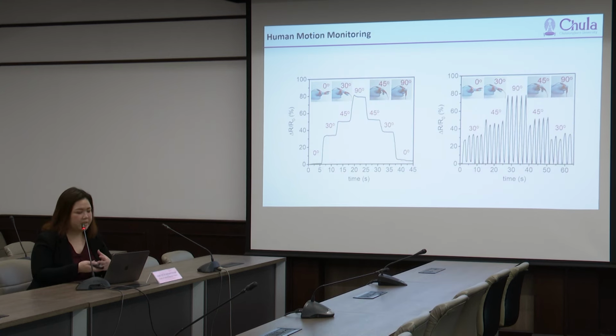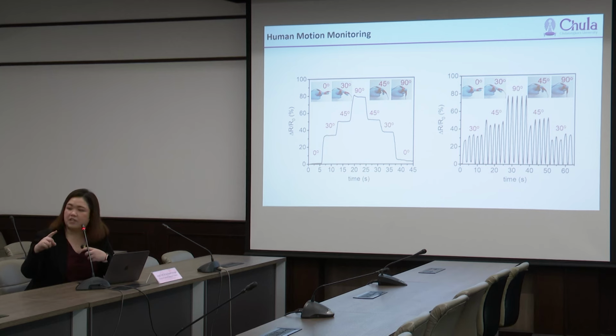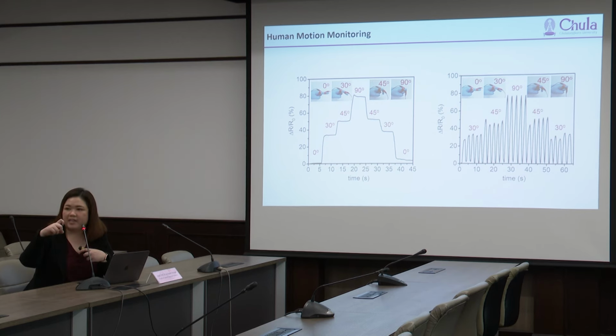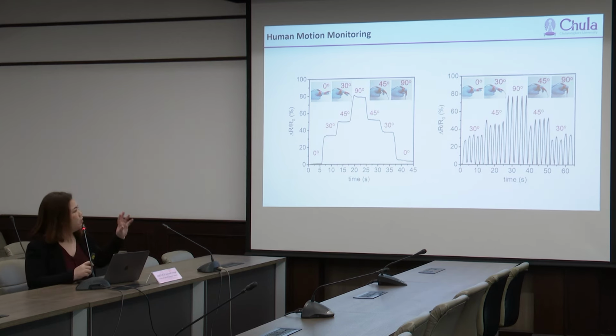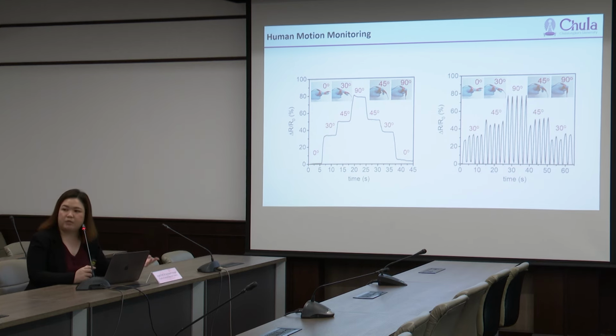So what we do next is that we print a strip and then put it on the finger. And then when you bend your finger at different angles, such as 30 degrees, 45, and 90 degrees, you can see that we can track that. You can see the electrical response in real time.